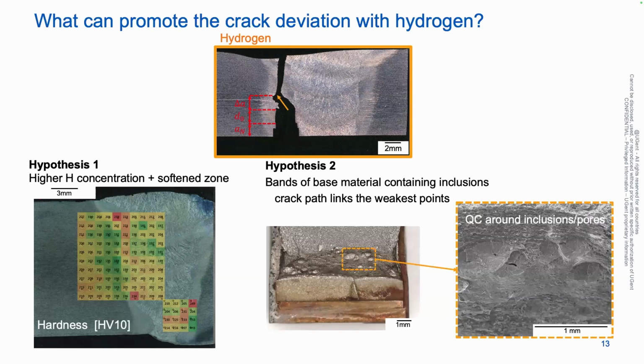A second hypothesis is, if we look at the fracture surface of the hydrogen charged specimen, that we see that there are regions of quasi-cleavage around inclusions. And the crack might link those regions, might link the inclusions while growing. So it's always searching for the weakest link in the path ahead.